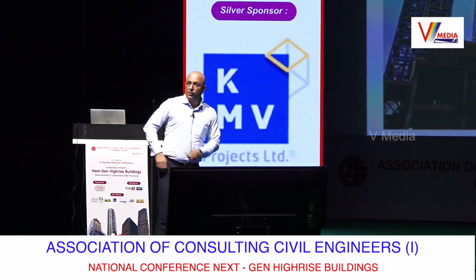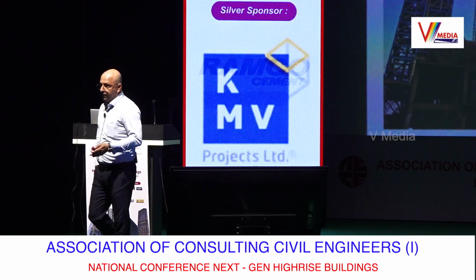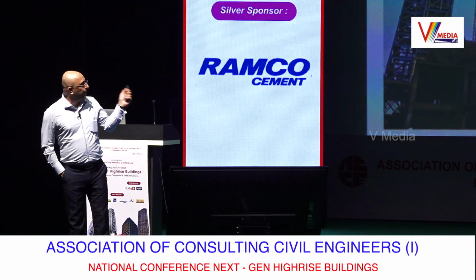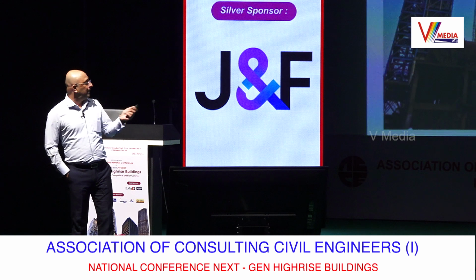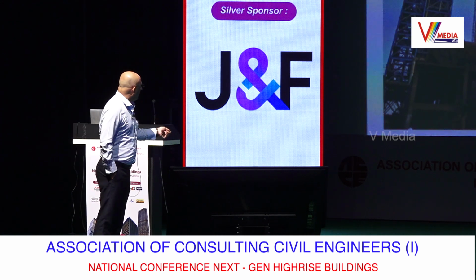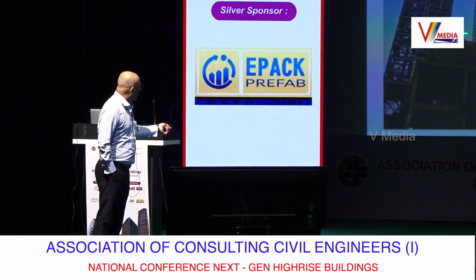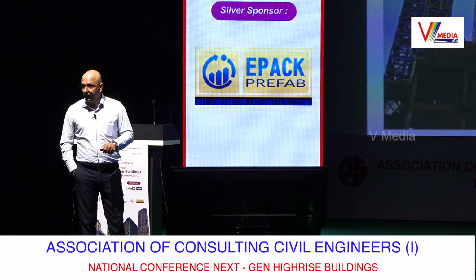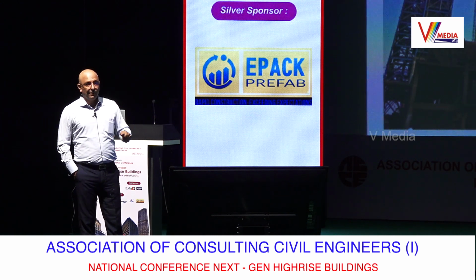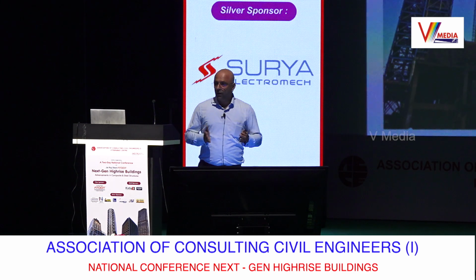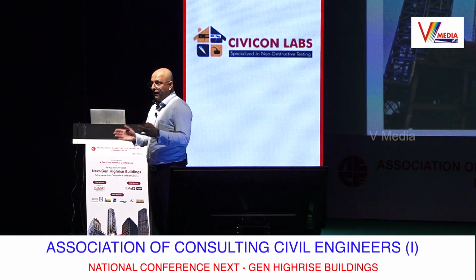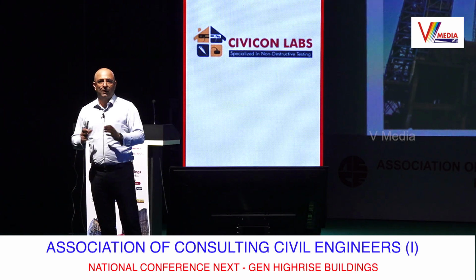The shutdown went on for almost 2 months, and this chimney was not designed for elevated temperature for a prolonged period. As a result, the lining just above the duct on both sides started collapsing, and when the lining collapsed, the concrete was subjected to 800 degrees Celsius. The concrete caved in, after that the steel melted and the chimney started buckling.